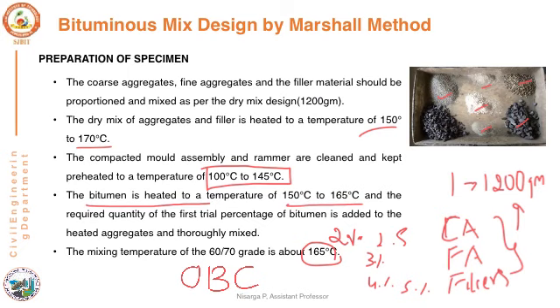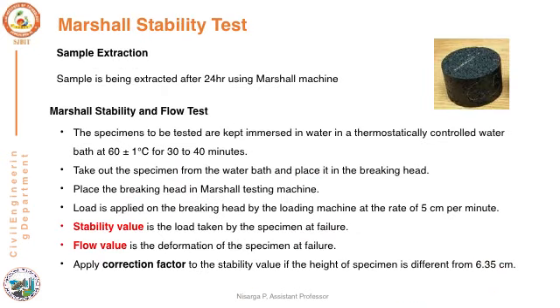Apply 75 number of blows on either side of the bituminous sample and compact the mix. The compacted specimen is then extracted out after 24 hours to ensure complete cooling of the bituminous mix material. The sample can be extracted using a manual extractor or Marshall machine. The extracted sample has to be heated to a standard testing temperature of 60°C, achieved by immersing the sample in a thermostatically controlled water bath for 30 to 40 minutes.